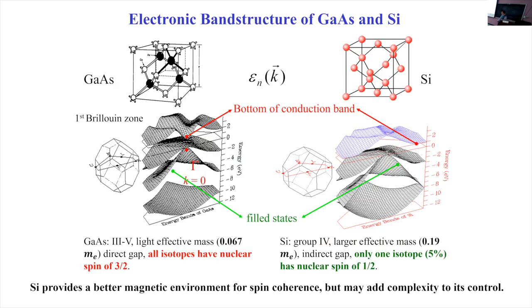And so for that, we need to go back to the basic material physics of silicon. Gallium arsenide has a particularly simple structure in terms of its band structure. The bottom of the conduction band in gallium arsenide is at the gamma point, the center of the first Brillouin zone. And the top of its valence band is also there at the center of the first Brillouin zone. So it's a so-called direct semiconductor. That's why electronically, gallium arsenide is a dominant material for those applications. And for qubit application, it also gave us a very simple structure where you can just describe the electron spin in gallium arsenide using an effective mass model easily. So still a single electron with a quadratic dispersion, it's just a different effective mass. And that effective mass is more or less isotropic in the 3D material.